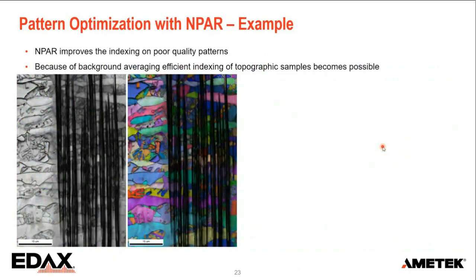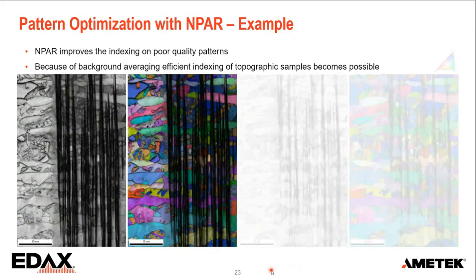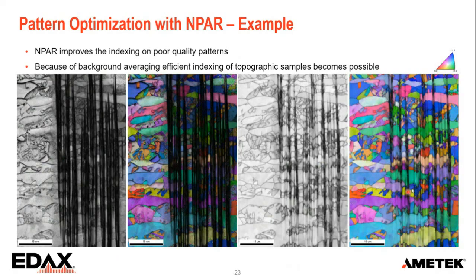Another benefit of this NPAR optimization that we can do afterwards is that you can average the background when it changes with surface orientation. So you can use it, for example, for topographic samples like fracture surfaces. Here I have an example of a FIB cut with horrible curtaining due to some artifact at the top. And normally, of course, we don't see anything in these curtains. It's just shadowed and there's no signal coming out. And when we apply NPAR to that, you can get a full indexing result. And you can truly see why they call it curtaining. You can just see the bending of the surface everywhere.